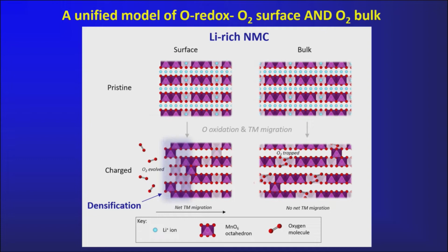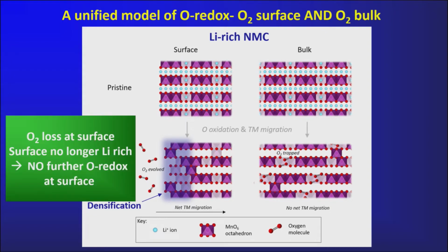And crucially, the surface, when it densifies, is essentially becoming stoichiometric. It's no longer lithium-rich. So when it reaches an NMC composition with no extra lithium, there's no mechanism for O2 loss anymore. And so the whole process sort of grinds to a halt at the surface. So the only other option now is for O2 to form in the bulk, and that's only possible when you get this structural reorganization to form those voids.